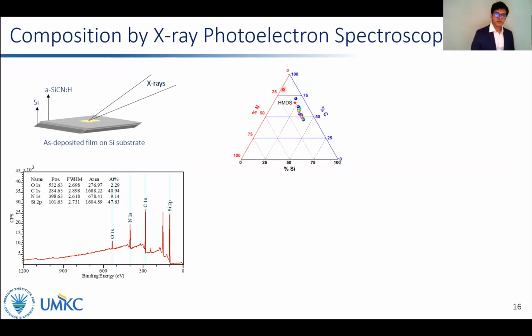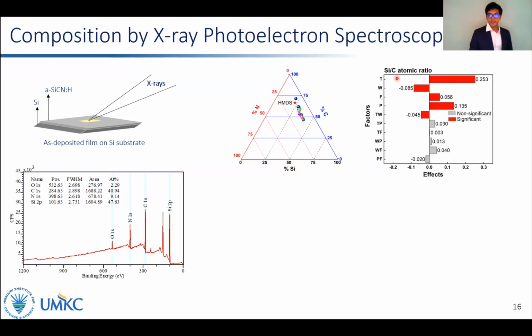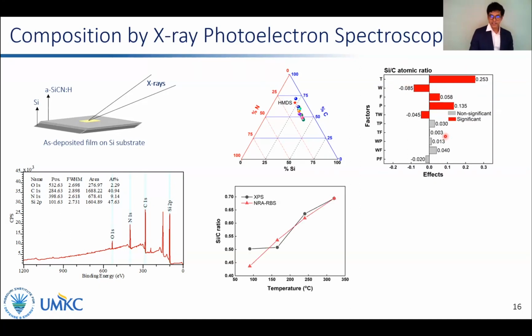We were able to tune the composition of the materials with respect to HMDS composition as a function of PECVD parameters. The variation was good, but not as drastic as we anticipated. For example, in the Pareto chart, the SiC atomic ratio was analyzed, and it tends to increase with increase in temperature.